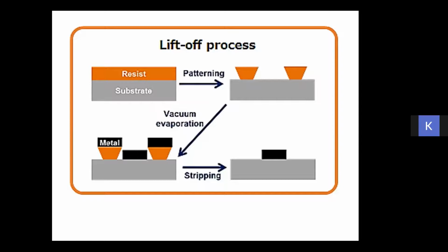Now you have to put that in an acetone solution, or basically pure acetone. Acetone actually kills the organic material. That means it will remove the polymer. And when it removes the polymer, it will remove the metal on top of it. So when the polymer gets dissolved, the metal over the polymer will also move away and get washed out.